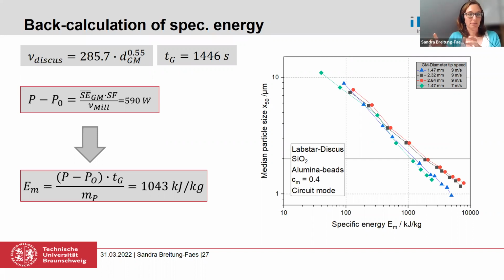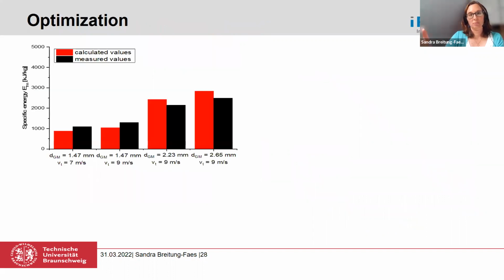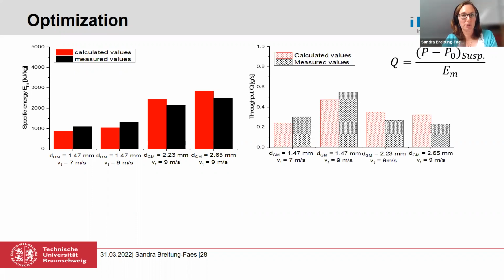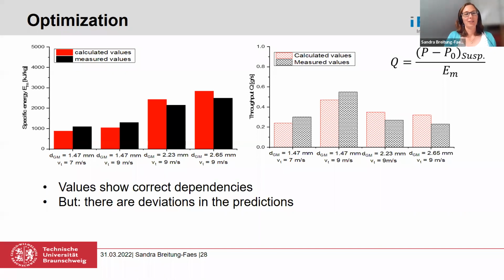And if you're sure with it and know your mill, then you can start playing and optimizing your mill in the way you would like to have. For example, here we have the specific energy values for the different experiments we did. And you can compare the calculated with the measured values. Sure, you see some deviations, but the dependencies were given in the right way. Or you can go further and calculate, for example, the throughputs. If you want to optimize your process with regard to the throughput, then you can see here that, okay, with increasing stirrer tip speed for the smaller grinding beads, the throughput is increasing. So the values show the right dependencies, but there are still some deviations.